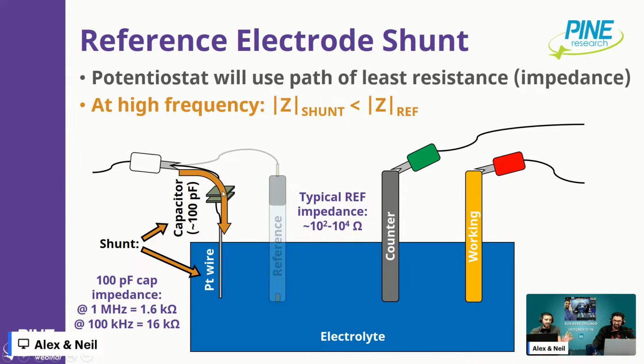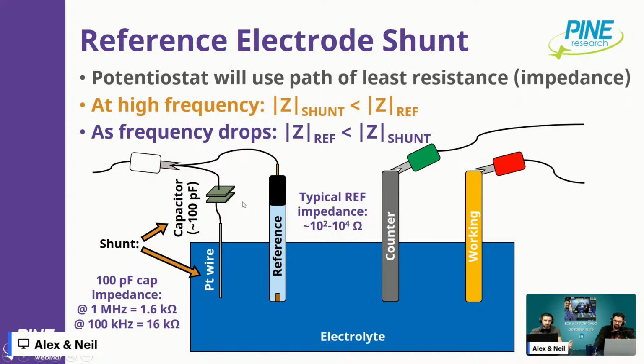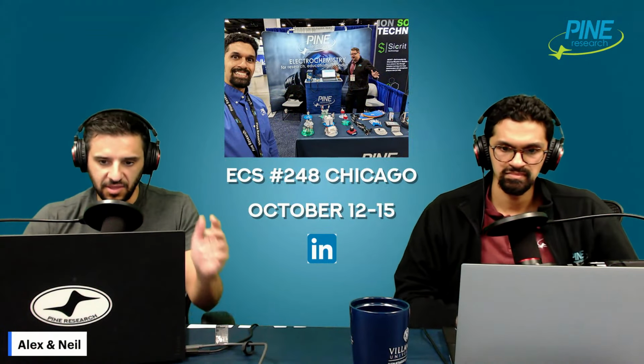So then as the frequency drops, to 100 kilohertz here in this example, the impedance of my shunt, my capacitor, goes to 16 kilo ohms. That's greater than 10 kilo ohms. So I start measuring through my reference electrode. So what it does is it allows me to remove the reference electrode's high frequency issues over a narrow range. And that depends on the capacitor choice you use and everything like that.